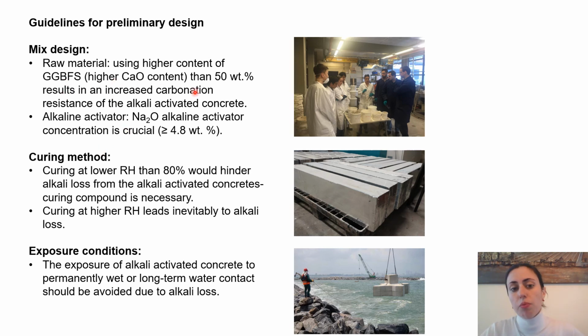So it is very important to use raw materials which have a high amount of calcium oxide in their composition. This really offers increased carbonation resistance. And for the alkaline activator, it's very important in the mix design that the sodium oxide is balanced, so that eventual leaching from the surface of alkali activated concrete during curing is not happening.